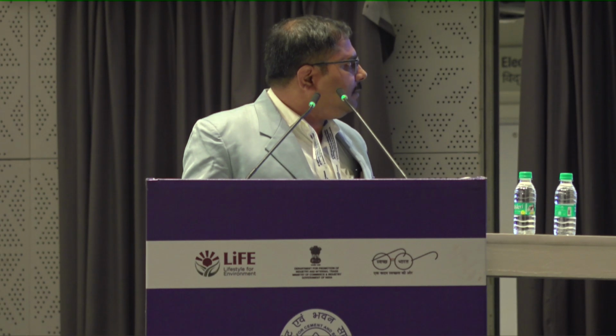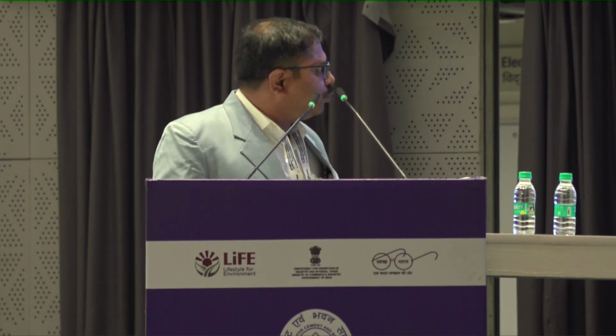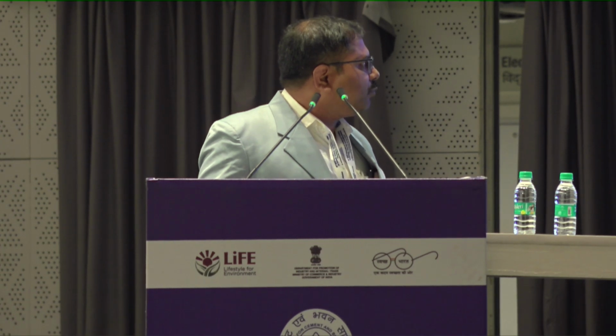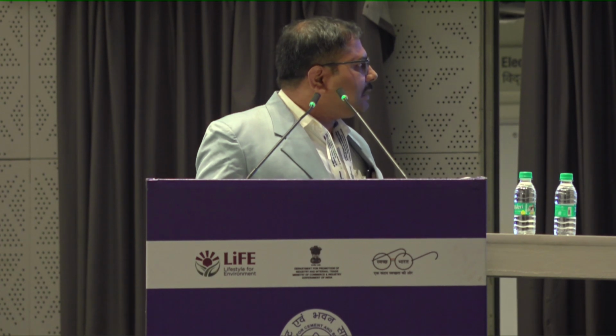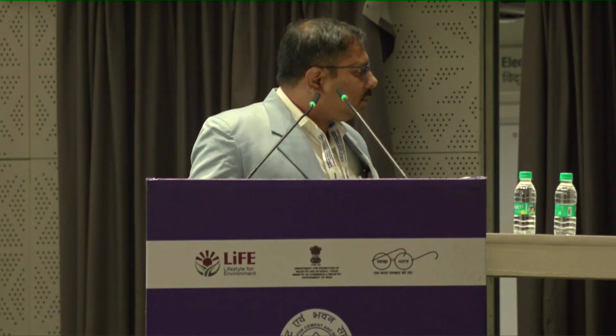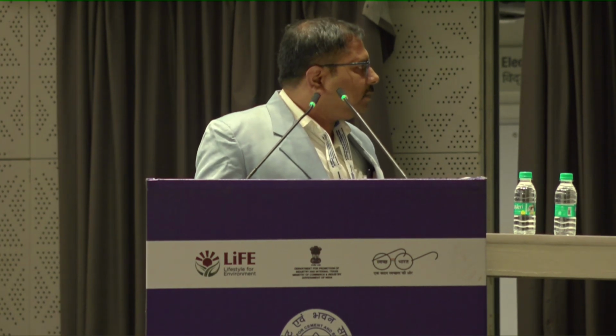This is the Indian standard requirement to produce LC3. It has been compared with PPC. The major thing is that the clinker would be in the range of 50 to 80%. If we use OPC 43 grade cement to produce LC3, then it would be in the range of 55 to 85%. Limestone would be in the range of 5 to 20%. Calcined clay would be in the range of 10 to 35%. Blaine would be minimum 400 square meter per kg. Loss on ignition would be maximum 10%. And strength is similar to the OPC 43 grade cement.